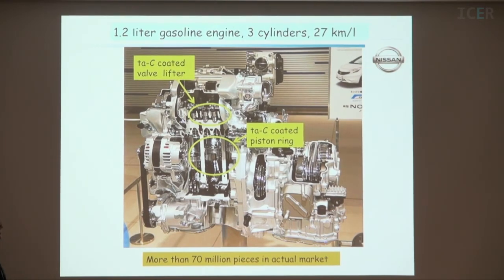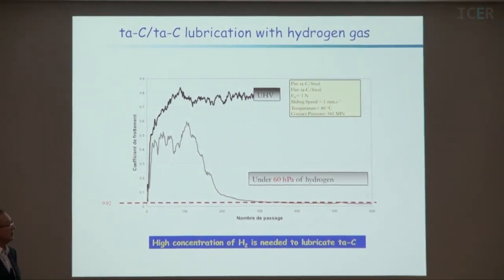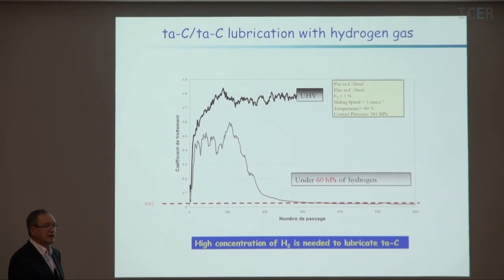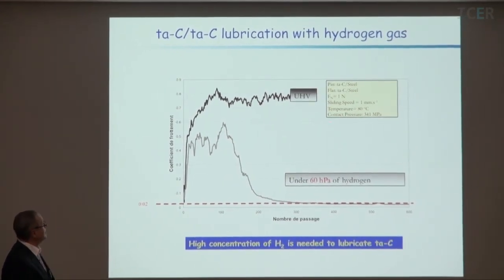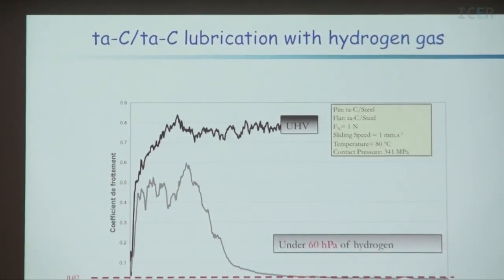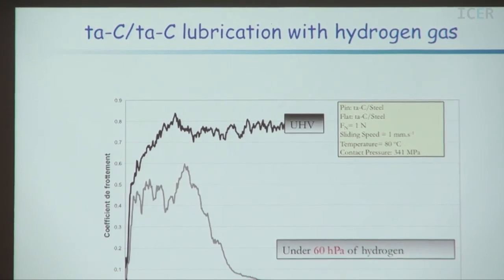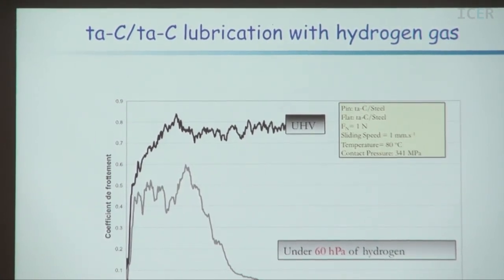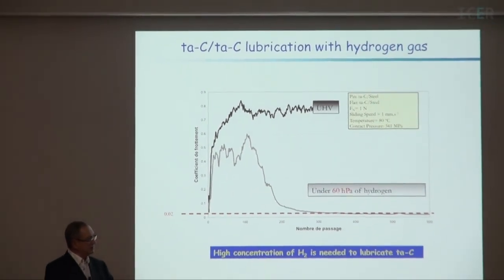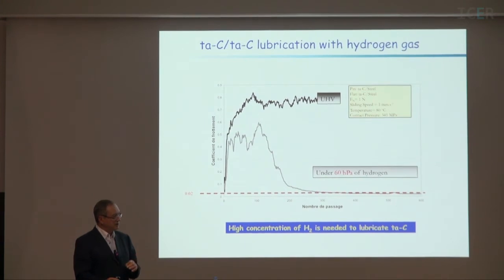So, again, we use a machine, but here we use the machine more simply. We just made the friction test in presence of the gas. For example, here we have the friction coefficient, and this is the number of cycles, for TAC. TAC is a hydrogen-free carbon coating. Very, very hard. Not as hard as diamond, but maybe 60, 70 GPa, and diamond is 100. Steel is 10. So 70 GPa is very hard.